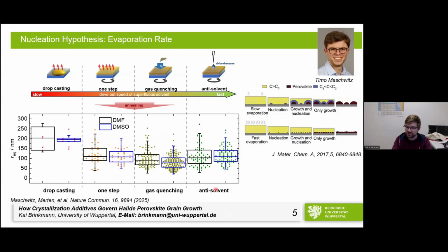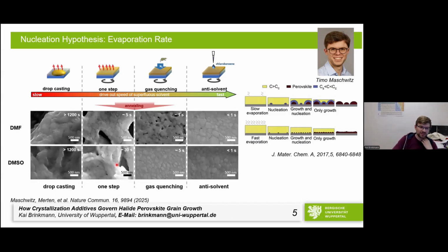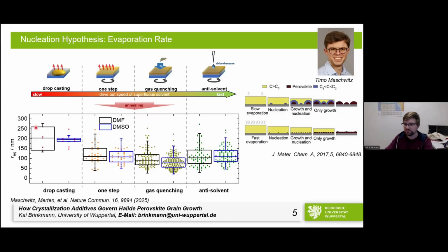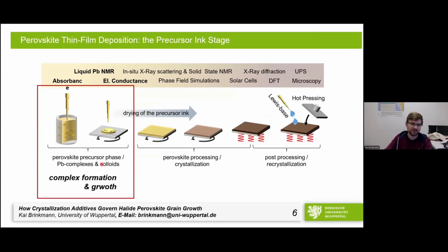If you look into the literature, this might not be surprising, but if we think about the classic nucleation approach, this actually feels a little bit odd, because if we're talking about time scales, for the precursor to turn darkish takes like 30 seconds. In the drop casting method, especially with the DMSO, it took minutes for the solvent to eventually evaporate. So this somewhat confused us. And so we were wondering, okay, maybe stuff happens before. Maybe the drying is not the problem. Maybe stuff happens in the precursor ink.